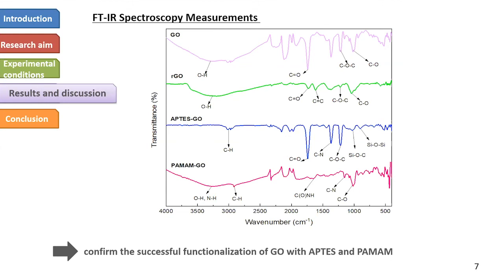In case of PAMAM modified GO, a new band emerges at around 1650 centimeters on -1, which can be attributed to the bending vibrations of the amide groups here. Furthermore, the characteristic absorption peak for carboxyl groups has vanished in the spectrum of PAMAM-GO, confirming that the reaction takes place between the amino groups of the dendrimer and the carboxyl groups of the GO.